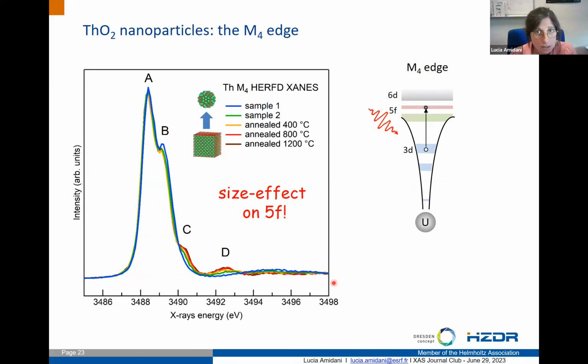And here you see this is the M4 of thorium. We have sample one, the as-prepared precipitate, just dried at 40 degrees. Then with mild annealing and strong annealing, we go from the blue to the dark red.